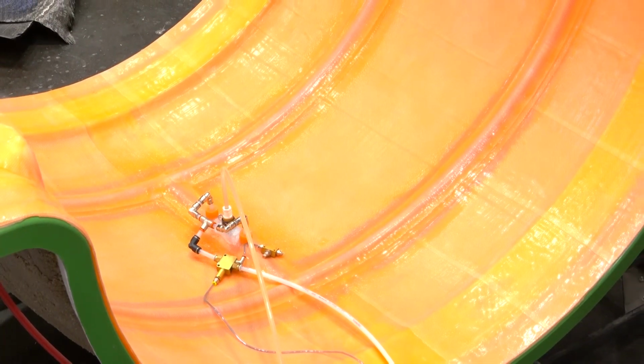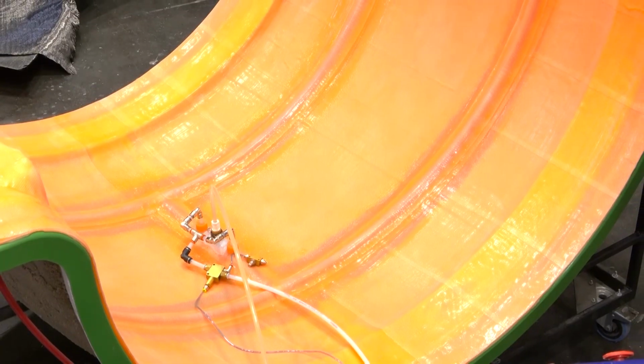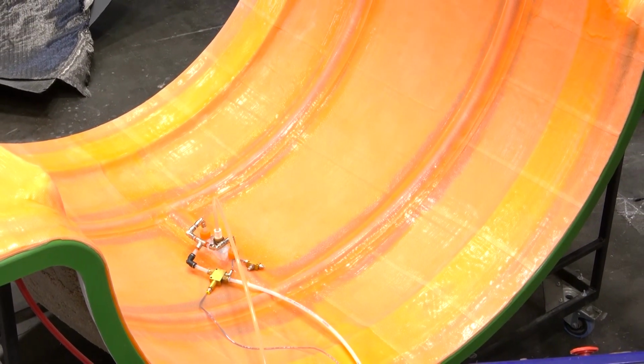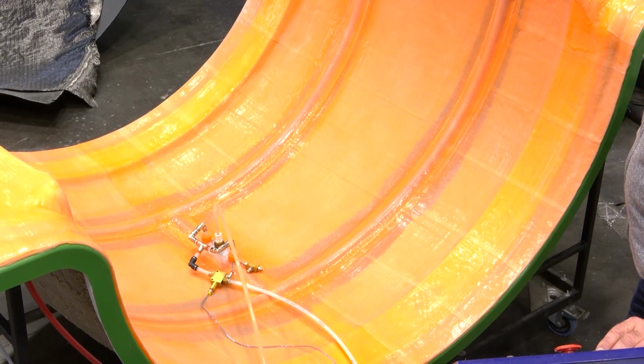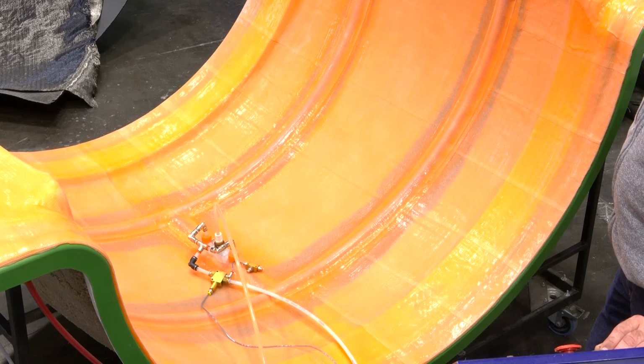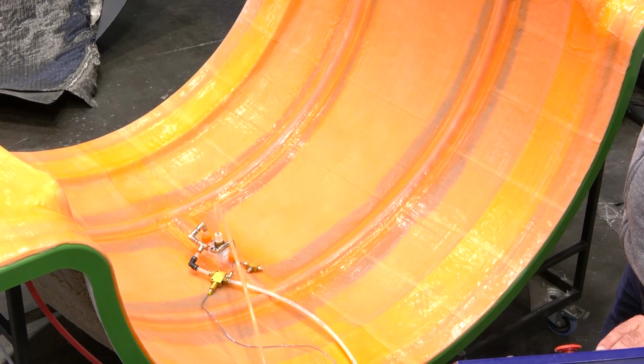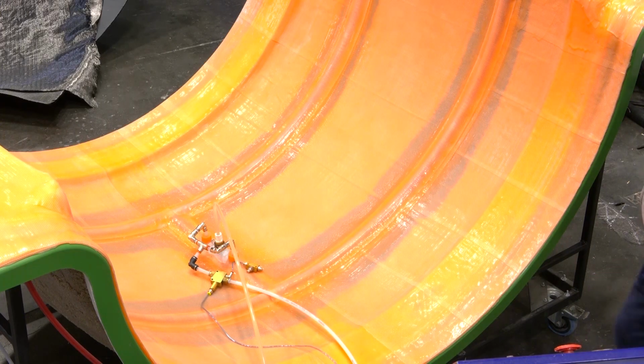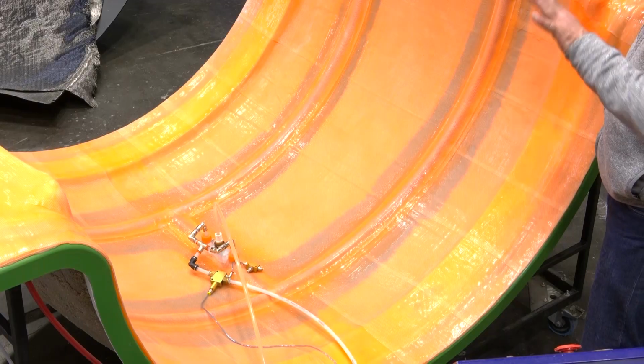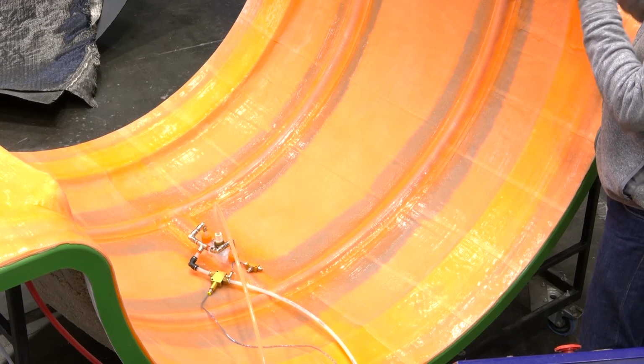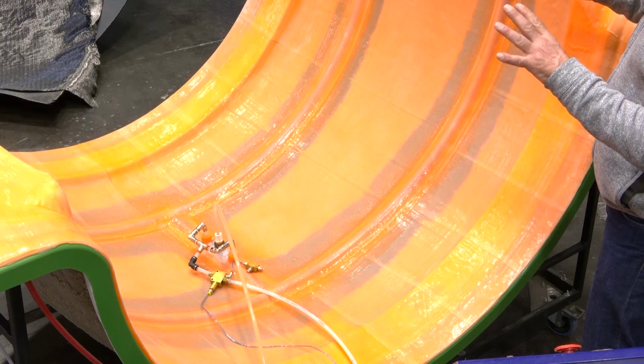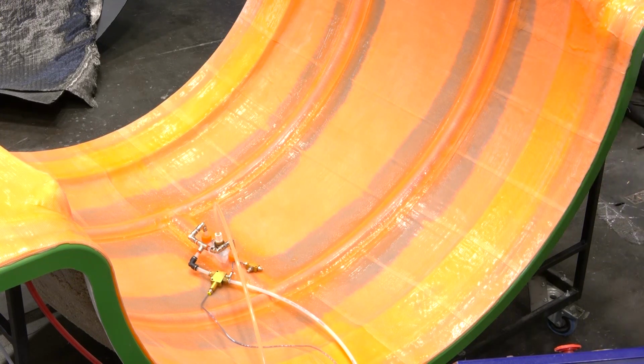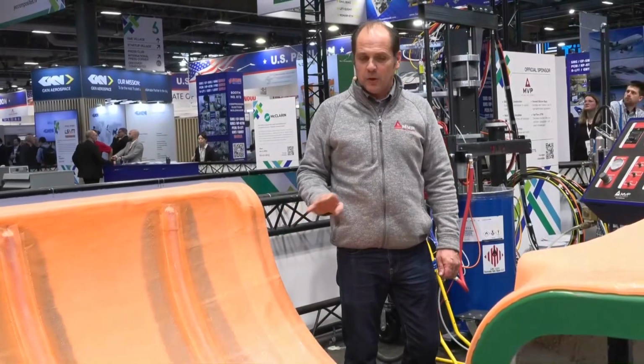So now we see the resin coming, arriving here step by step. Yeah. So you see the resin flow. So now I can slow down a little bit the machine. There is no need to rush and to go too fast. And you see now exactly how the resin flow is regular. We are on the full carbon without any flow medium on the top of that. And because of the groove, we control the resin flow. The groove gives 38 grams of resin per square meter, no more than that.